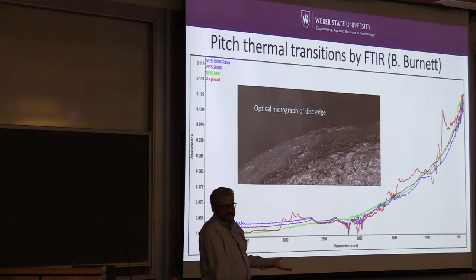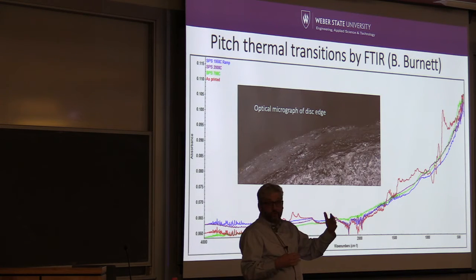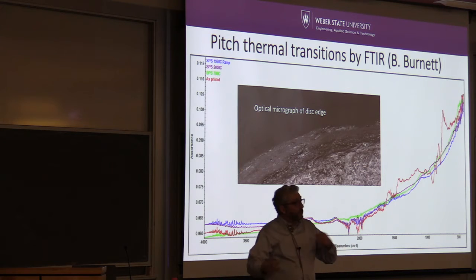So you stick it in the FTIR and you look at it. Here's the FTIR fingerprint, the red, when we just printed it, and the coal pitch has only seen like 70 degrees C. FTIR turns out to be a really powerful technique when you have a lot of side chains and functional groups, because the IR modes are really good for distinguishing asymmetry. And so you get really nice fingerprints of molecules when you have asymmetry. What this showed us was that as we went up to 700, 1950 and 2000, we completely lost these fingerprints because we lost all of our side chains and all of our functional groups. All you've got now is carbon bonding with carbon.